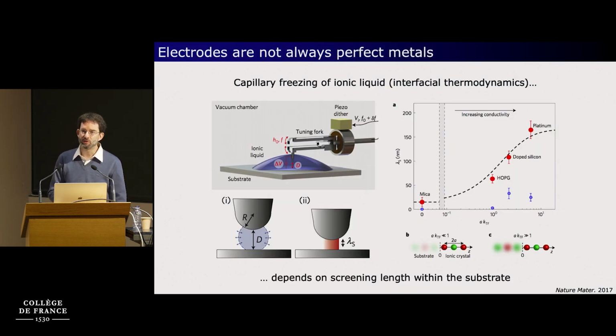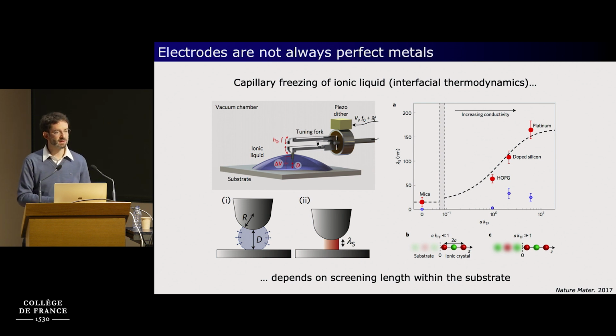Another aspect that I'm going to discuss in the second part of my talk is that electrodes are not always perfect metals. And to illustrate that, I'm going to use one of Lyderic's works, in which they investigated the capillary freezing of ionic liquids, which is related to interfacial thermodynamics. In these experiments, they used the tip of an AFM probe to confine an ionic liquid between the tip of the probe and a substrate. As they approach the tip, they observe a change in the mechanical response of the fluid from a liquid-like behavior to a solid-like behavior, which can be interpreted as capillary freezing, and the distance at which this capillary freezing occurs depends on the nature of the substrate, and they could show that the results can be rationalized if you consider various substrates that are more or less metallic.